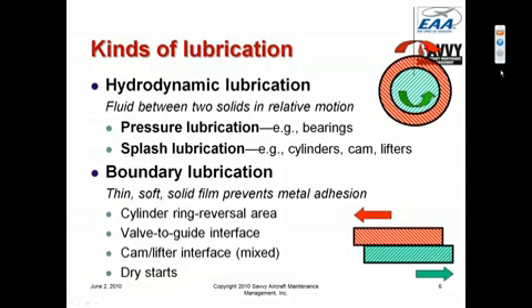The cam and lifter interface is kind of a mixed lubrication situation. There's very little pressure between the cam and lifter when the valves are closed, and so hydrodynamic lubrication is typically adequate. But at the critical point where the toe of the cam is lifting the lifter and opening the valve against very, very high forces of valve springs and high pressure in the cylinder, there's not adequate hydrodynamic lubrication, and so we have to rely on boundary lubrication for the cam and lifter interface at the area where there's the most force between the parts, specifically where the cam toe is lifting the lifter.